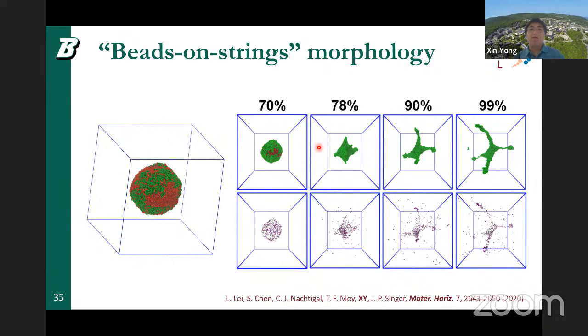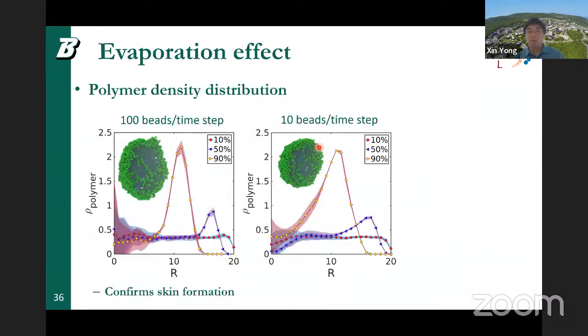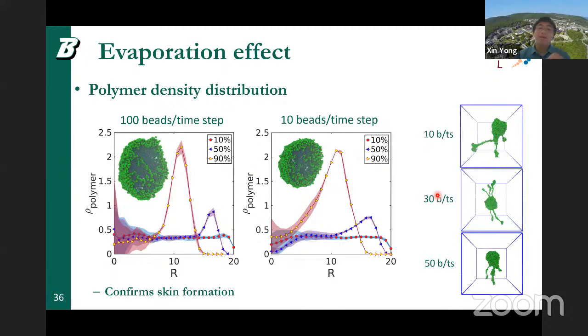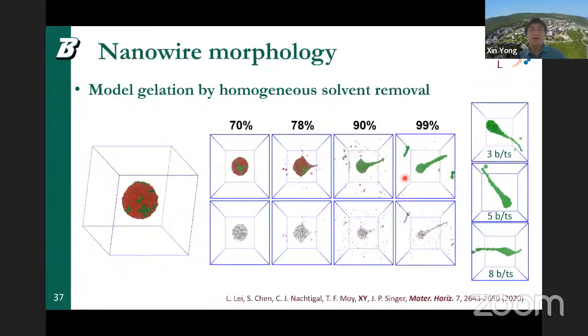Now we confirm that our density is non-homogeneous by looking at the polymer density distribution, where we see that we remove the beads at different rates, but overall with these ranges, we see a very clear polymer shell indicated by this density distribution. So this confirms the skin formation. And so the bead-on-string is very robust in these regions with these rates.